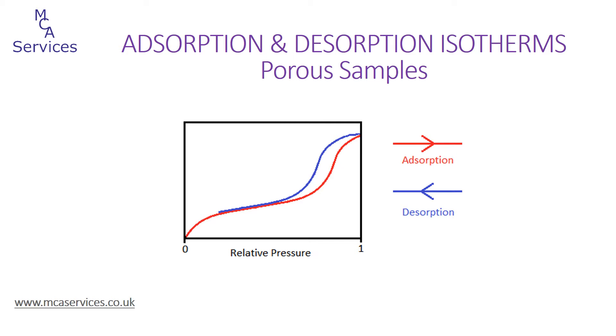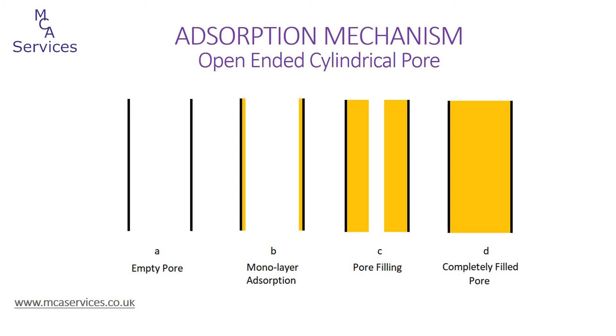The hysteresis is due to the physical processes of adsorption and desorption being quite different. Pore filling during adsorption is by a process of condensation, whereas pore emptying during desorption is by a process of evaporation. The mechanism of pore filling during adsorption occurs from the pore walls inwards to the centre of the pore, via a process of successive multilayer adsorption of adsorbate on adsorbate — so adsorption occurs from the sides of the pores inwards until the pore is completely filled.